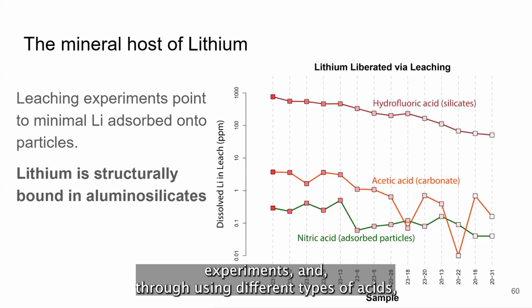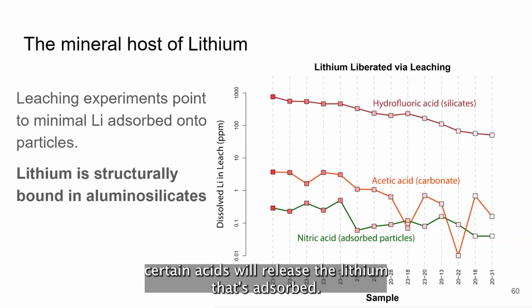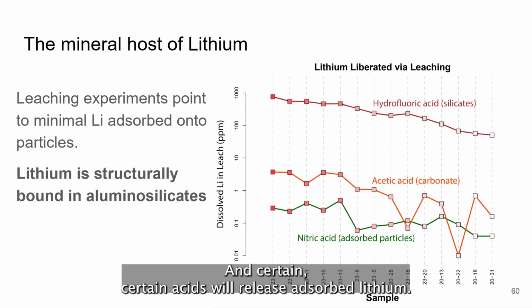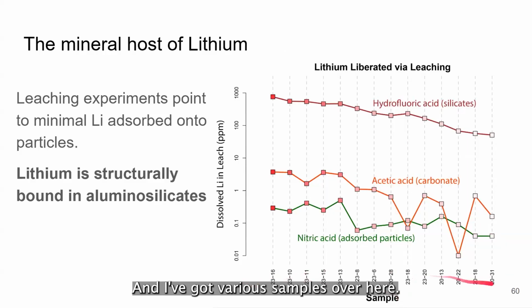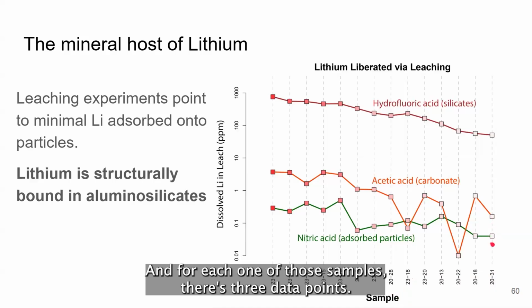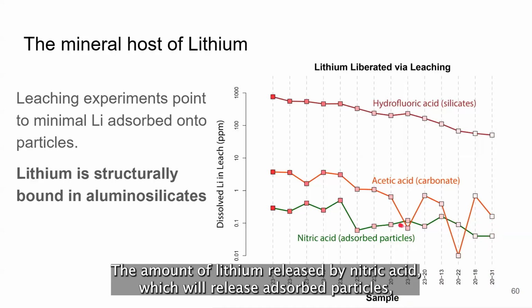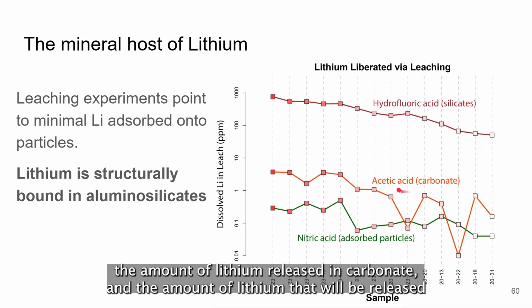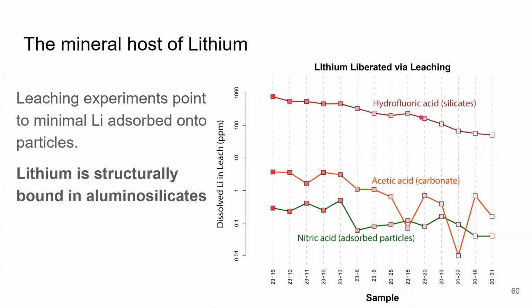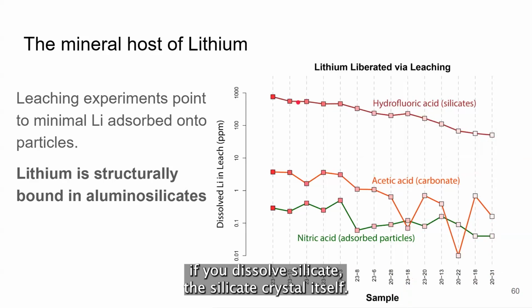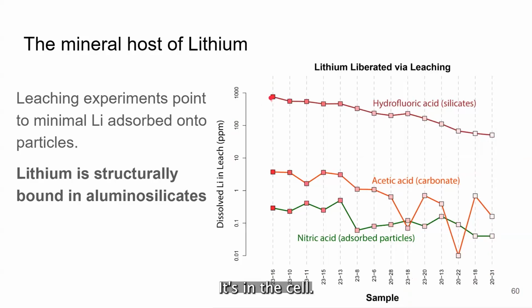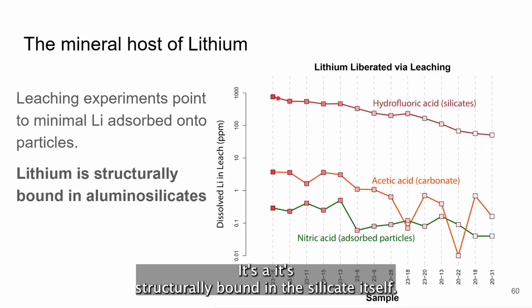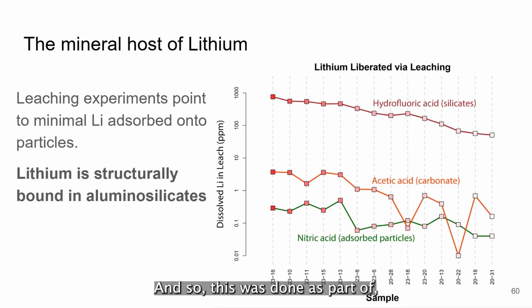We've done various leaching experiments, and certain acids will release adsorbed lithium. I've got various samples over here, and for each one there are 3 data points: the amount of lithium released by nitric acid, which will release adsorbed particles, the amount released in carbonate, and the amount that will be released if you dissolve the silicate crystal itself. And this is a log scale, and it's not even close. It's structurally bound in the silicate itself. This was done as part of some ongoing lithium isotope work that Liz Andrews has done. So thanks, Liz, for this great data.